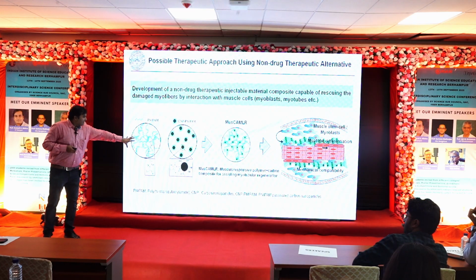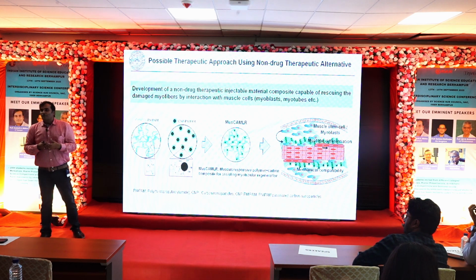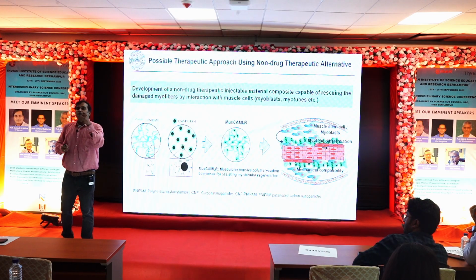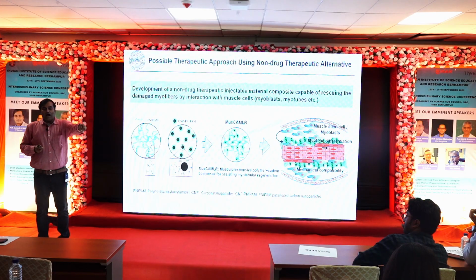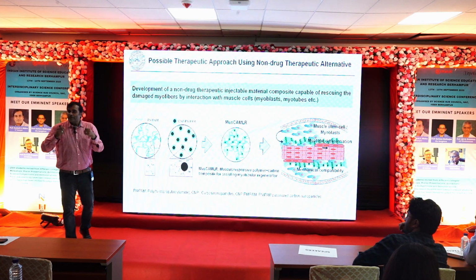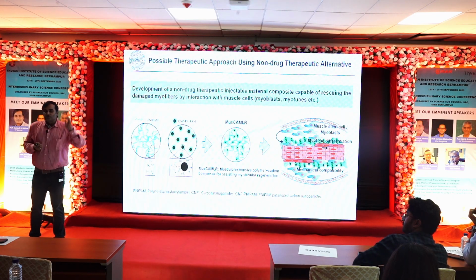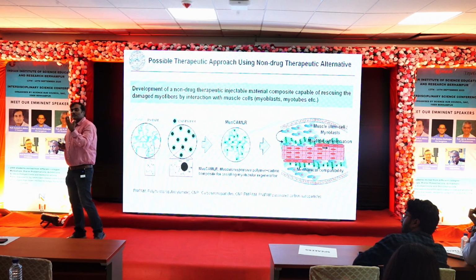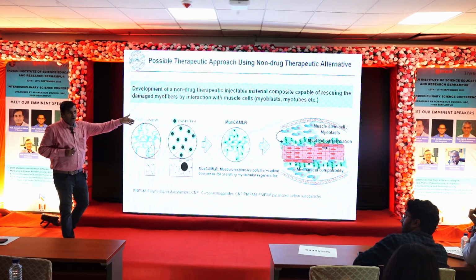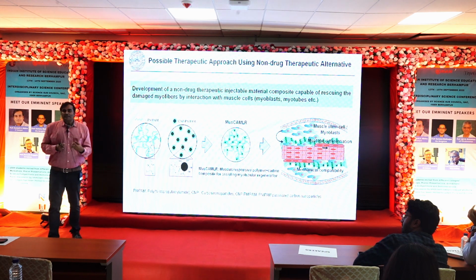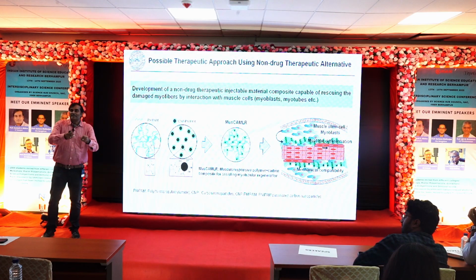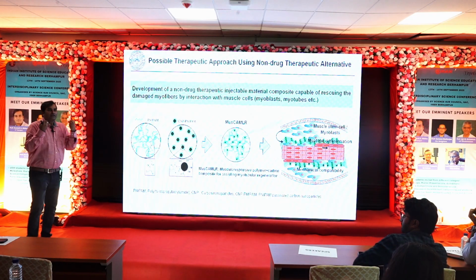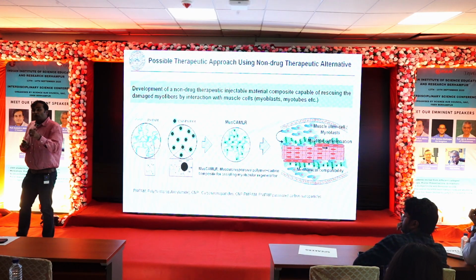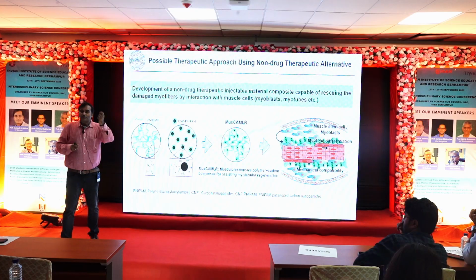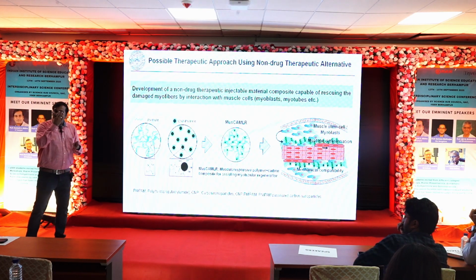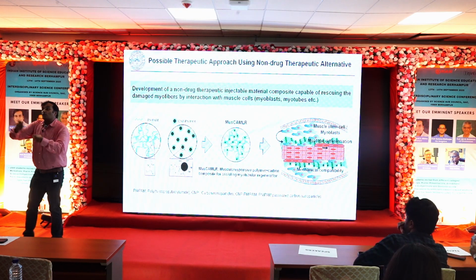It entirely depends on the way side chains of this polymer play an important role in making this network. What did we do? We played a little bit with hydrogen bonding which is happening between the side chains. We put in a carbon material which disrupts the chain-to-chain interaction and enhances its own hydrogen bonding property, and that pushes the critical temperature, which is called the lower critical solution temperature, LCST, close to 36.5. Now our initial intention was that this should be good enough to enhance the activity of the stem cells in the muscle tissue. But we got another benefit as well, and that was the mechanical strength. We were only looking for whether we can somehow change the solution to gel phase transition close to 37, which should be good enough.